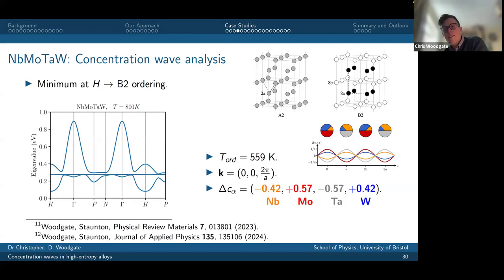And if I look at the chemical polarization, what I see is that niobium and tantalum, minus 0.42, minus 0.57, the concentrations of those elements are going down, when the concentrations of molybdenum, plus 0.57, plus 0.42, molybdenum and tungsten, are going up. So what this is describing is niobium and tantalum moving to one sublattice, with molybdenum and tungsten moving to the other. And so this B2 ordering, it turns out, is actually driven by that valence difference between the elements present in the composition, okay?